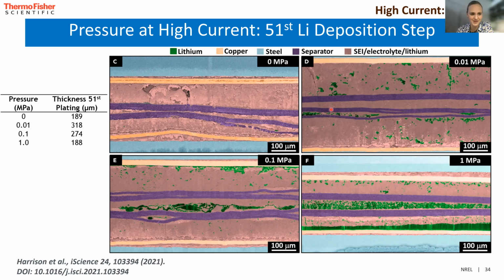And as you go to higher pressure, there's more lithium left over, but it's really dispersed throughout the cell, and it very quickly is removed from the counter electrode at the bottom. But we see a lot of it deposit within the separator or between the separator layers. And commonly we saw the separator layers fall apart after cycling.